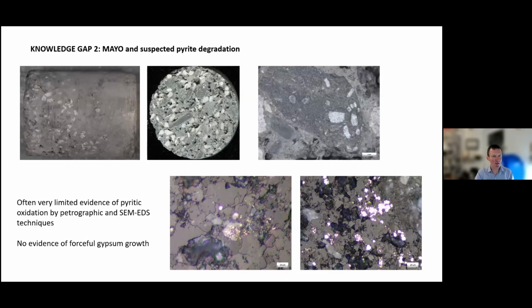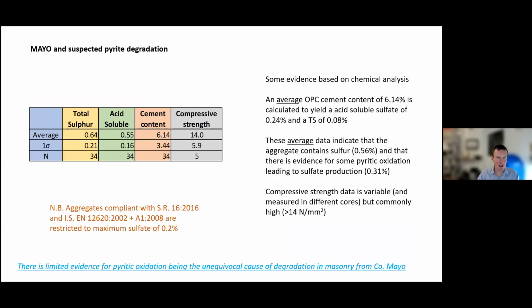Knowledge gap two I'm going to mention is Mayo and suspected pyrite degradation. And this has concerned me for some time now that there's often very, very limited evidence of pyritic oxidation seen by petrographic, by thin section petrography and SEM EDS techniques. And there is almost no evidence of forceful growth of gypsum in any of the material. And I've looked at a lot of this material. There is a bit more evidence based on the chemical analysis.